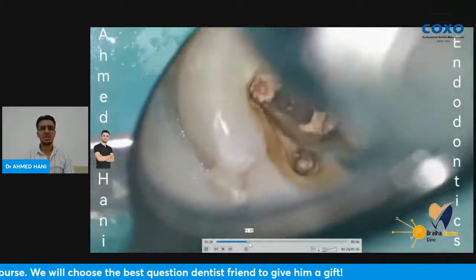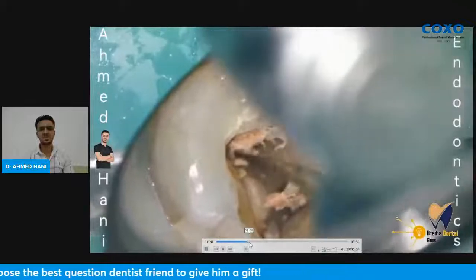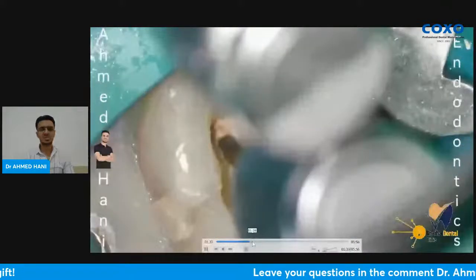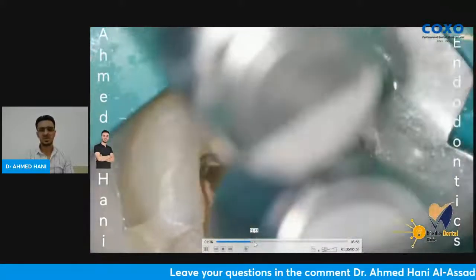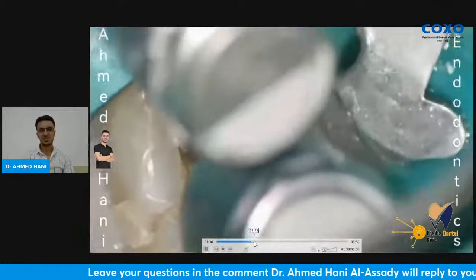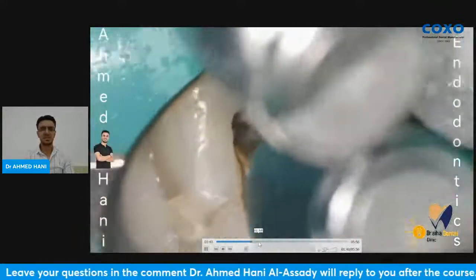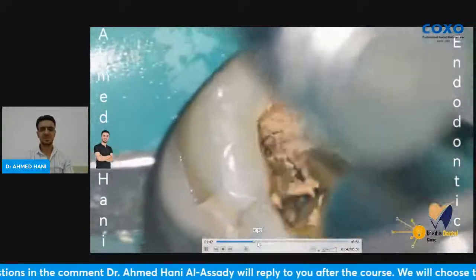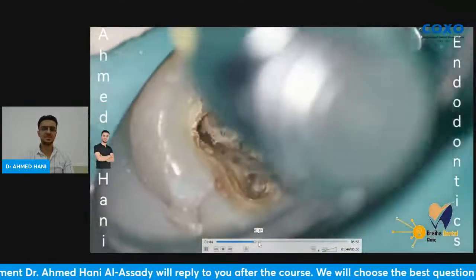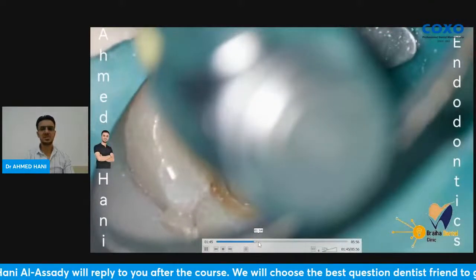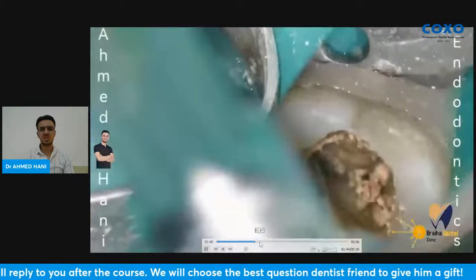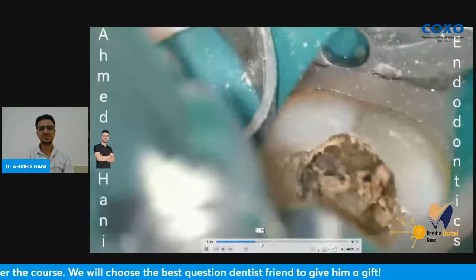We cannot use this technique with resin based sealers or zinc oxide based sealers, because zinc oxide will resorb and has shrinkage when set, so it leaves spaces. But calcium silicate based sealer, no, it expands when set, zero shrinkage, bactericidal, alkaline pH. Calcium silicate based material is a filling material, not just a sealer.